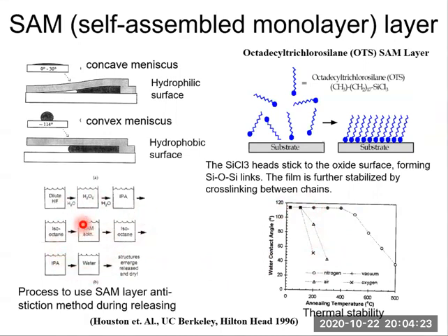This is a process to use the SAM anti-stiction method during releasing. After HF etching, I will use a dilute HF to remove the sacrificial layer underneath. Then we replace the solution with H2O2, hydrogen peroxide. The purpose of this step is to form a native oxide on the silicon substrate, because the trichlorosilane heads stick to the oxide surface. So we need to somehow oxidize the silicon surface. Then it's replaced by IPA, alcohol solution, then iso-octane solution, then the SAM solution. In this step, the self-assembled monolayer is formed on the silicon surface.